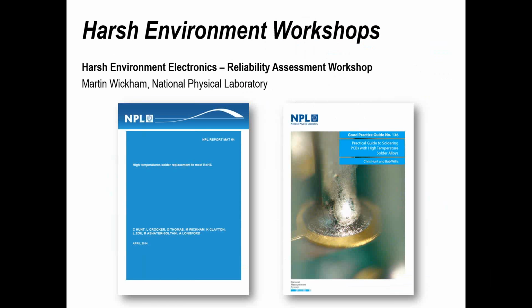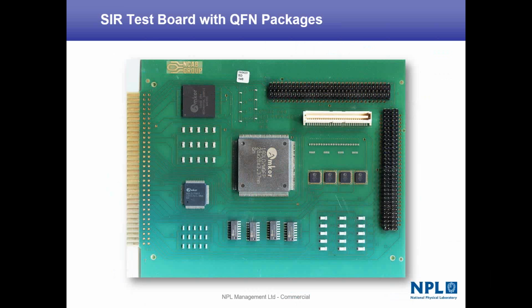So that's the sort of our overview of experience with those materials, and some of the results we got after aging again is included in one of those reports, and they're both available to any delegates that come to the conference. One of the specific areas that Martin will be covering is some work on a new test method which was developed by NPL to look at cleanliness assessment, yes, but also to look at semi-real life environments. Traditionally, we've had 95-95 testing, 95 RH, 95 relative humidity. We've also looked in the past with using different types of environment, but what the automotive industry tend to use is a specification or a test method kind of for the automotive industry, and what we look to do is